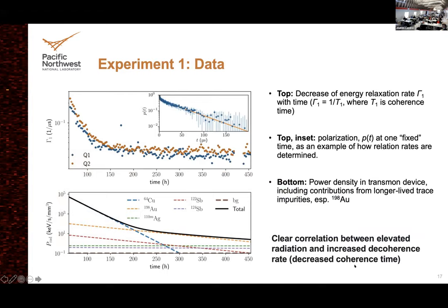We did the experiment. I'm showing the energy relaxation rate — which is just one over the coherence time — as a function of time, as the copper-64 source decays with its 12.7-hour half-life. Each measurement of energy relaxation rate is determined by a fit to the polarization curve showing the double exponential kick at the bottom. It takes a few minutes to make that measurement, and we can do it repeatedly while the source is decaying. The total power into the superconducting materials is modeled from the known calibrated activity of the source — mostly copper-64, but trace impurities with large neutron activation cross-sections produce gold-198, giving a longer-lived tail at later times.